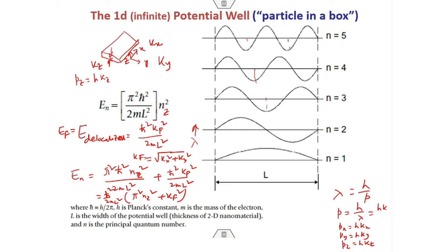And therefore, the smaller the grain size, the lower the electrical conductivity for 2D nanocrystal materials. That's very clear. Because it's confined in the Z direction, electrical conductivity will decrease. But still, an electron can have unfettered, undisturbed motion along the plane. But there also, depending on the grain size, this motion will be hindered because of scattering events. But that is a classical effect, actually. So you have both the quantum confinement effect and the classical-level presence together. That's what happens. Okay? I hope I have made it clear.